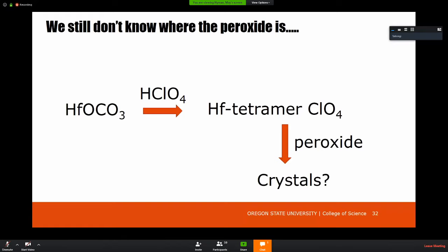So again, we can simulate the scattering data of the tetrahedron, and then we can monitor the reaction solution of this 10 peroxides per 1 zirconium solution and see what forms on the way to obtaining this tetrahedron that crystallizes out of solution. What we found is something much larger forms. And we know it's larger because we've got a shift in the Guinier region to low Q region. And it's something quite pure. And we know that because we see this oscillation here.